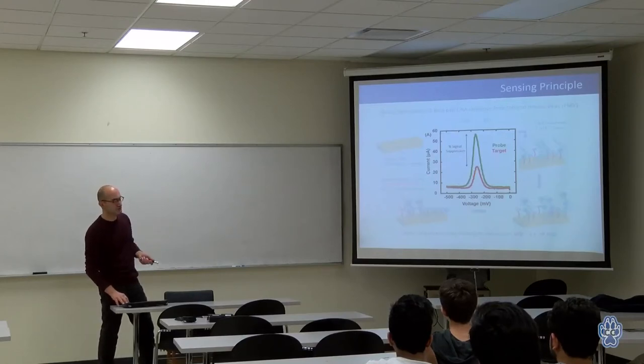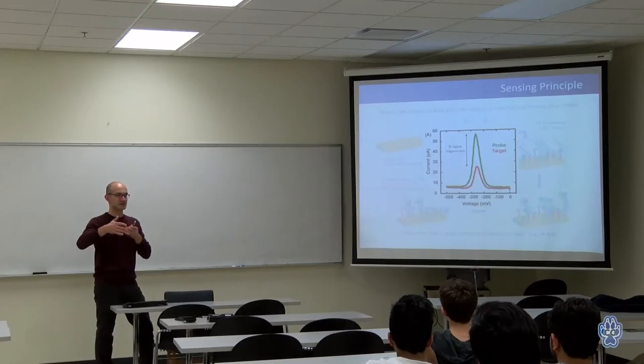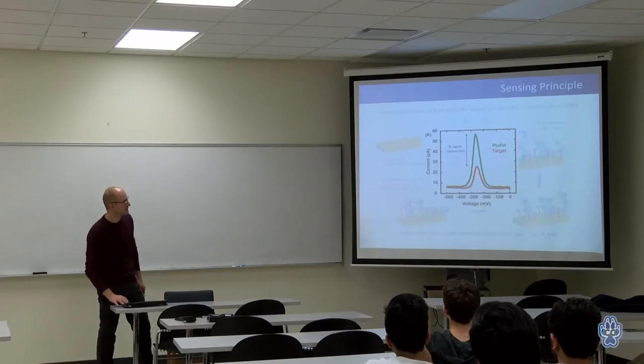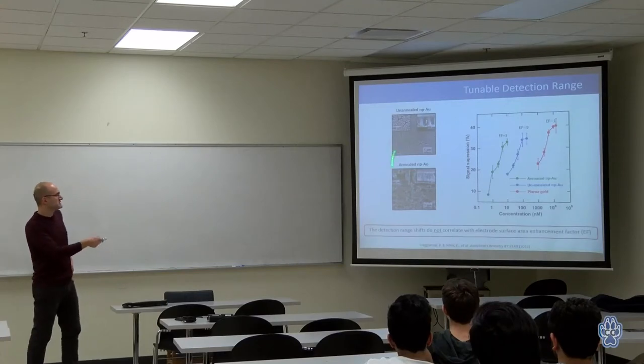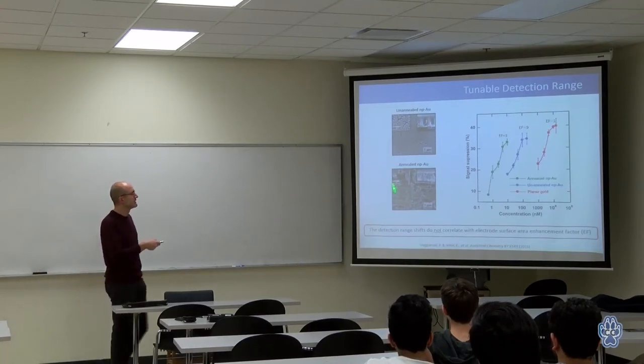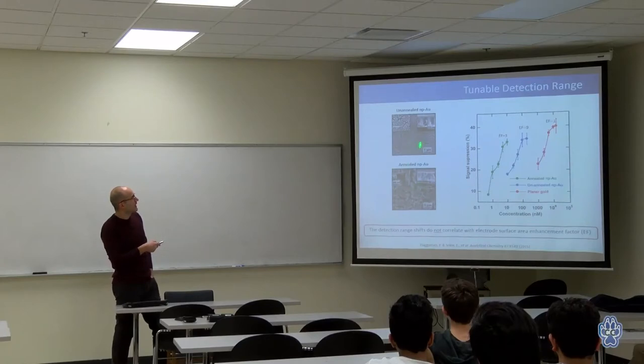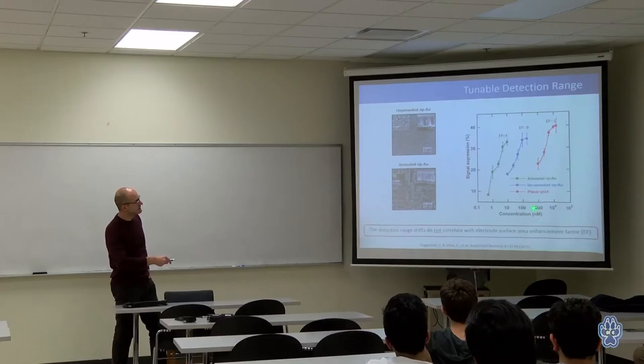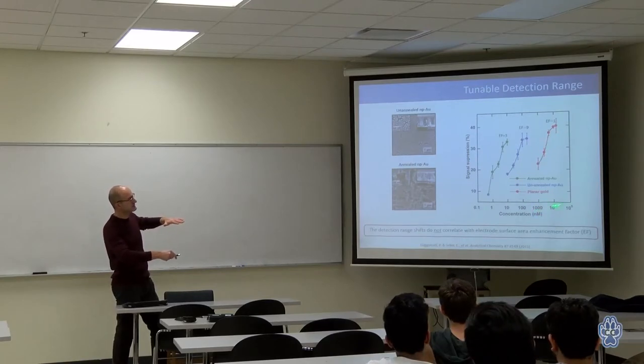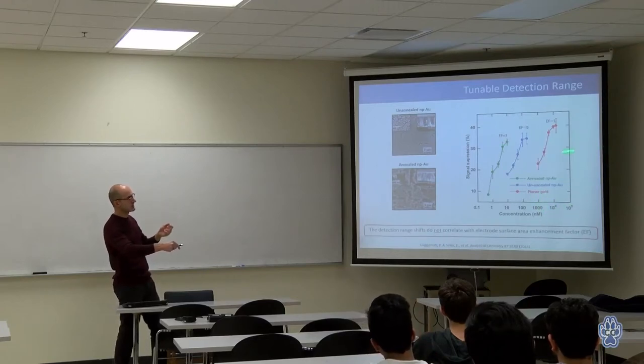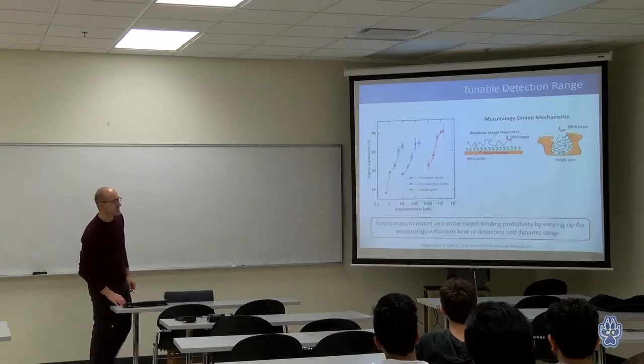Basically, you want a lower limit of detection and a dynamic range tuned to the concentration of the molecules you are trying to detect. Since we can modify the morphology very easily, we've looked at how changing the morphology changes the dynamic range. The dynamic range is the concentration of those DNA molecules that we are trying to detect in a solution. If you use a planar surface with no structuring, you can only detect in this one micromolar range. But when you go to the porous structures, you can actually begin to drop. And the reason for this is actually